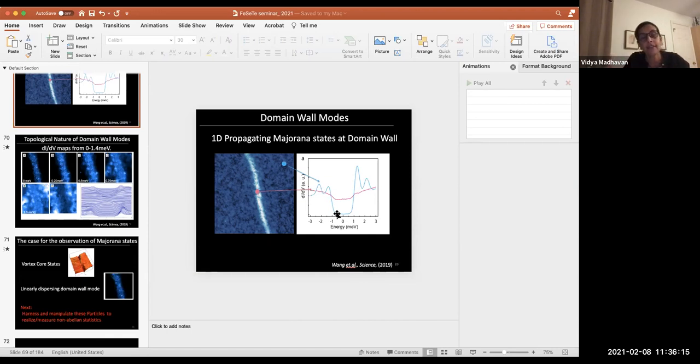You turn on a magnetic field, and in the vortex cores it sort of looks like a spinless p-wave. You have these kinds of phase shifts in the superconducting order parameter, then you can get Majorana dispersing states. But at the boundaries of the system, you don't get helical Majorana modes. I see. Mm-hmm.